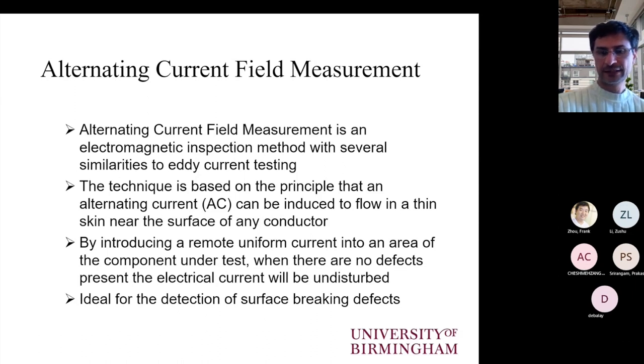So ACFM is designed for surface breaking defect assessments, rather than defects that are hidden below the surface. In theory, it is feasible to also inspect below the surface, but this requires specialized experimental configurations which are not really used by the industry. So in the industry, it is only used for surface breaking defects.